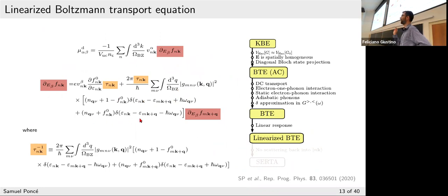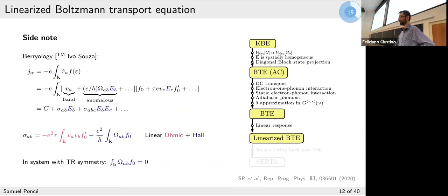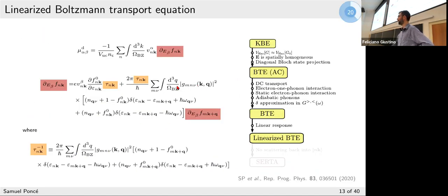So everything is included. What I was saying is that people have been trying to avoid computing the electron-phonon matrix element ab initio, and they've used models to describe it. There are some models like deformation potential in which you approximate the electron-phonon matrix element with a model formula, with some parameters. Deformation potential can describe acoustic modes relatively well, but it doesn't describe optical modes. So you also have Fröhlich models to describe the optical modes, and you could try to add many different contributions from many different models.